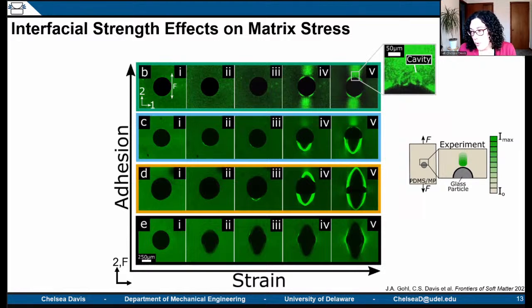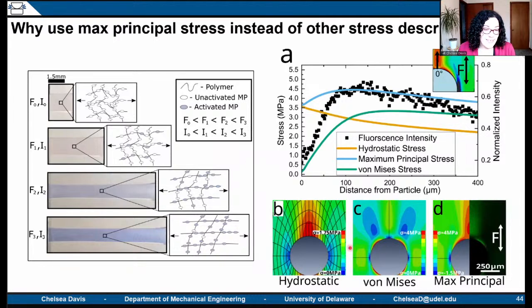So we went through a whole series of trying to understand which is the appropriate stress descriptor to utilize in this case. On a single molecule scale, mechanophores, to my understanding, only activate in tension. You have to have a fully extended polymer chain plus a little to pop the mechanophore that we're looking at. So on a molecular scale, the answer is tension and only tension. We are working with nearly incompressible materials. I think the Poisson's ratio is 0.49-ish.